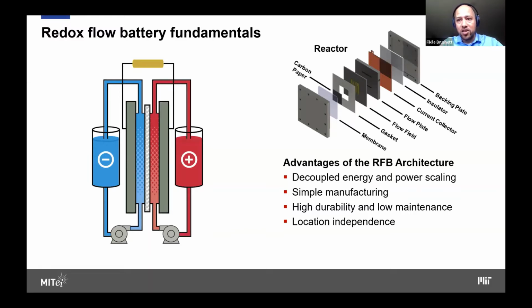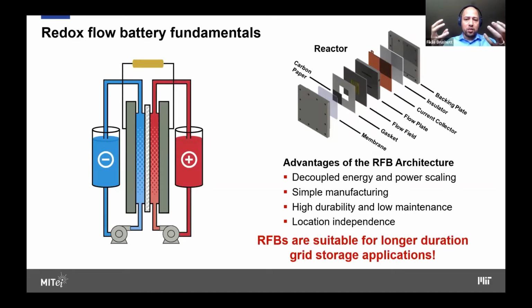However, there's no free lunch. And that's what this last click is here for. You're losing energy density when you have a system like this as compared to lithium ion, because your active materials are dissolved in electrolyte and stored in external tanks rather than a compact cell as you'd have for a lithium ion type battery. And so for this particular system, it looks more and more attractive the longer and longer duration energy storage you have. As the tanks get larger and the reactor gets smaller, you're asymptotically approaching the cost of the materials in the tank. The reactor becomes a smaller and smaller component. And so that energy cost gets lower and lower until you get to the materials in the tank.